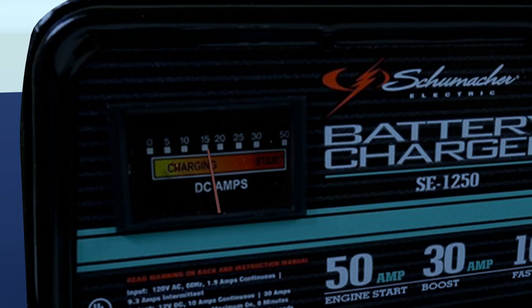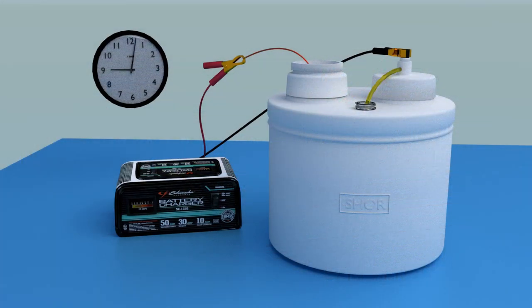Please note, if instead of refining an ingot or bar of metal, you are either stringing rings on the wire or using a nickel anode, then the amps will never drop to zero. The amps will drop to about 4 and remain there, because the wire or graphite rod will continue to conduct electricity. Dissolving time will vary with the amps. Typical dissolving time at 15 amps is about 1 hour per ounce of metal. So 5 ounces will usually take about 5 hours to dissolve at 15 amps. Lower amps will increase the dissolving time, while higher amps will shrink the dissolving time.